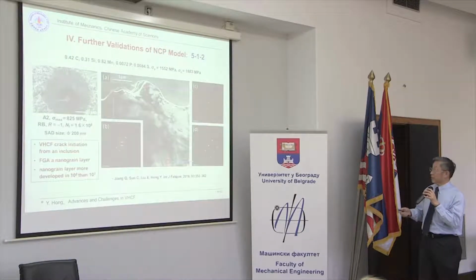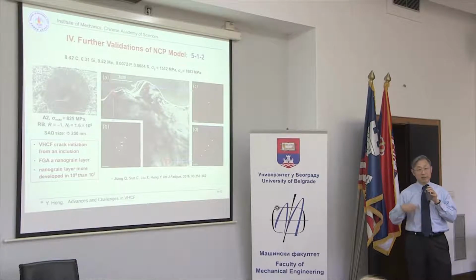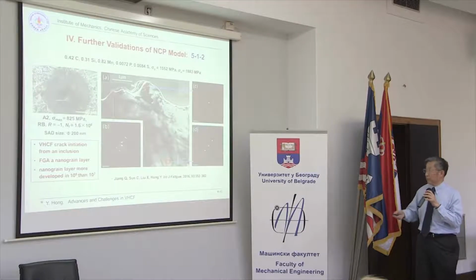But for the case of 10^8 cycles, it's a much longer fatigue life. And the microstructure refinement is much more evident than in the previous one. So we said that the origin is an inclusion, and the FGA is a nanograin layer, and this nanograin layer is more developed at 10^8 cycles than at 10^7 cycles.